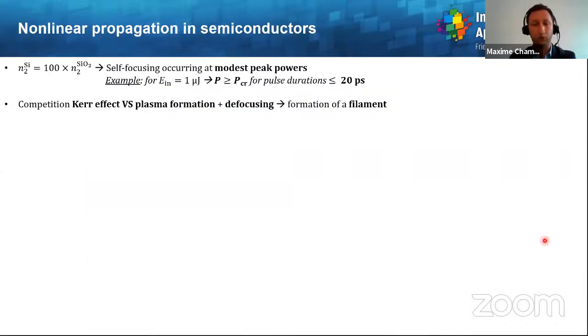And when one wants to explain that, one has to recall that silicon is a medium where the propagation is highly nonlinear, for the reasons I mentioned previously about the nonlinear refractive index, which is 100 times higher than the one of fused silica. For instance, if you consider 1 microjoule input pulse energy, which is pretty typical, the good order of magnitude for laser processing applications, then the peak power will be higher than the critical power for self-focusing for pulse durations below 20 picoseconds. And this value of 20 picoseconds is extremely high. And thus, as previously described, there will be this competition between Kerr effect and plasma formation together with defocusing, leading to the formation of a filament.